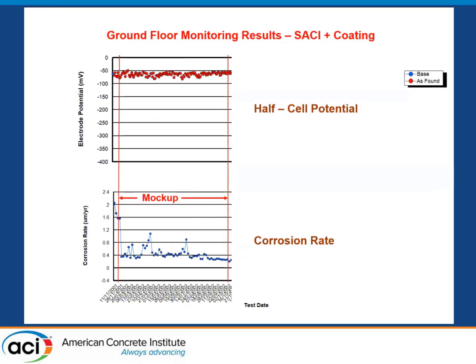In the other area where they used the inhibitor plus the coating, you can actually see here that there is almost a fairly quick drop in the corrosion activity. Yes, some spiking initially, but over time that really began to flatten out, didn't have so much of the erratic behavior. So the rates in this one actually started a little bit lower than where it was just coated, but they were reduced down to passive, and they remained at passive throughout the 1 year period. So based on this, the engineer felt that the combination of the inhibitor and the coating was really a good solution given the problems that they were combating.